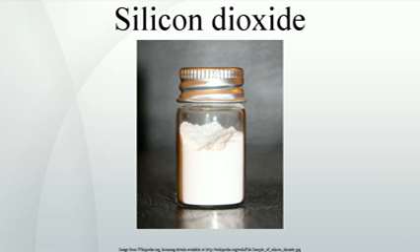In dimeric silicon dioxide there are two oxygen atoms bridging between the silicon atoms with an SiOSi angle of 94 deg and bond length of 164.6 pm, and the terminal SiO bond length is 150.2 pm. The SiO bond length is 148.3 pm, which compares with the length of 161 pm in α quartz. The bond energy is estimated at 621.7 kJ per mole.